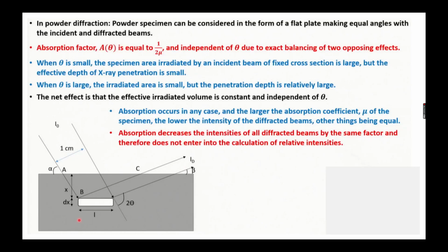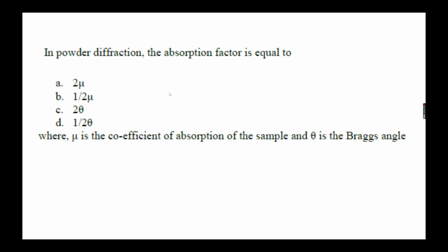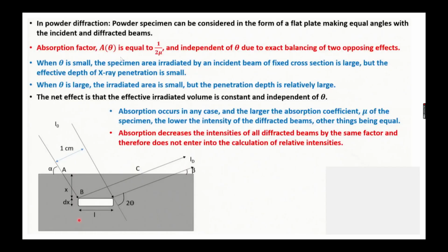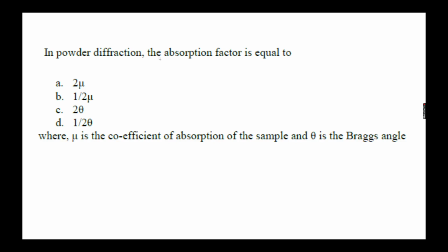So it is saying that when there is absorption, it will decrease the intensity of your diffracted beam. When your theta value is large, the irradiated area is small, but the penetration depth is relatively large. So here it is asking about the absorption factor equal to 1 upon 2 mu, where mu is the coefficient of absorption. So the answer is B.